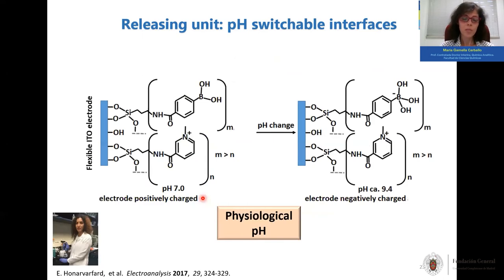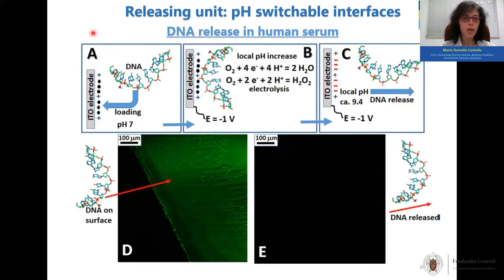We developed several systems based on this mechanism, but I wanted to highlight this application in which we prepared a switchable interface on flexible electrodes that is composed of these two substances, the boronic acid and this amino compound. This is interesting because this surface is positively charged at pH 7, which means that we can work with this system in physiological conditions. If we apply a pH change, then the boronic acid becomes negatively charged and we can release our drug in a controlled way.